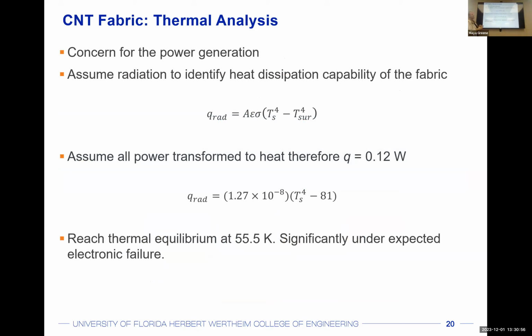We decided to model that via radiation in order to identify the heat dissipation ability of the fabric, to make sure that any of the power being drawn by one section of that fabric, in a worst case scenario, if we assume that all transforms to heat, was handled. We ran that radiative calculation and found that the thermal equilibrium was reached at 55 degrees Kelvin. That is under any expected electronic failure of that CNT fabric. We just wanted to make sure that we weren't going to experience any of that failure. So again, our limiting case is not concerned with the heat generation of the CNT fabric.